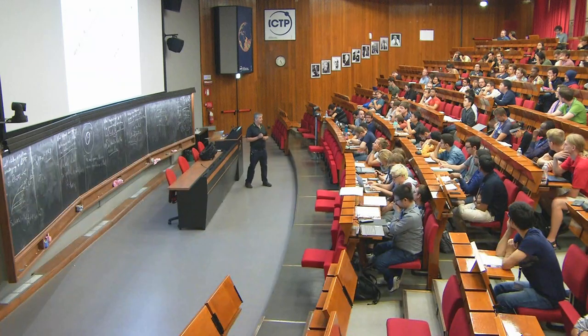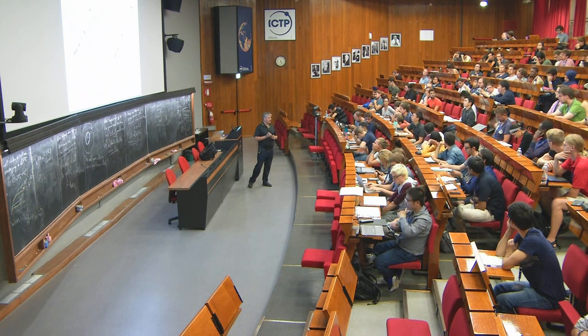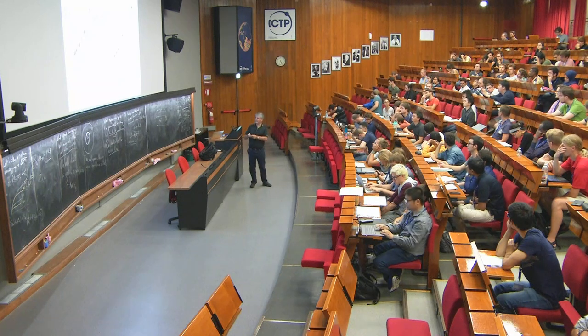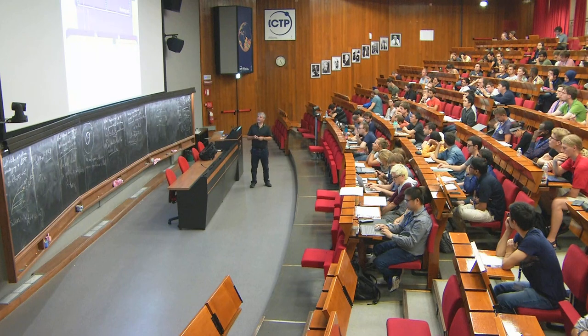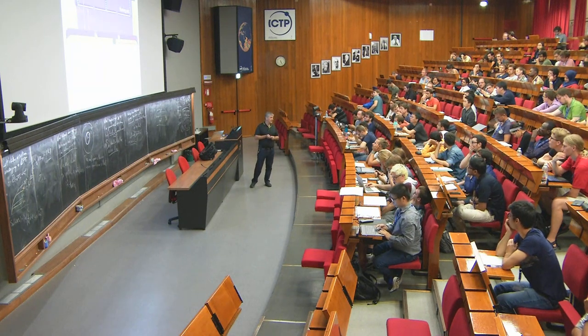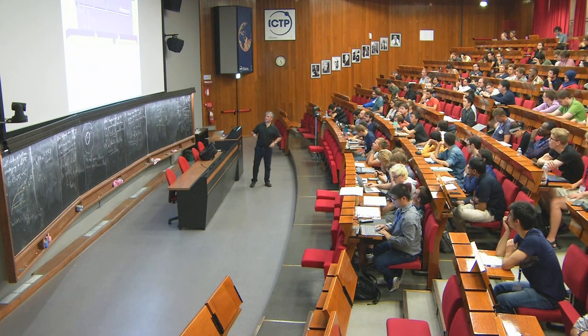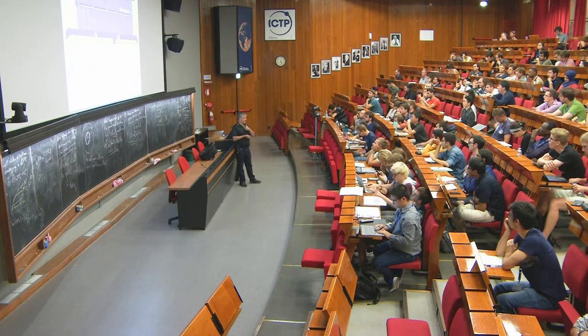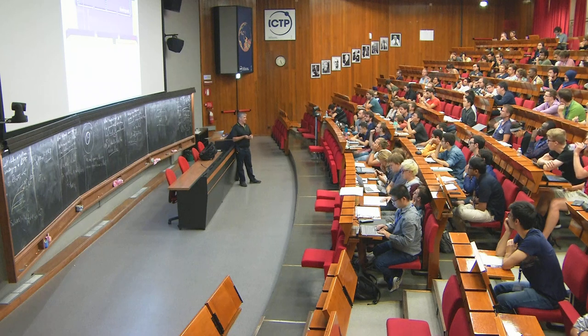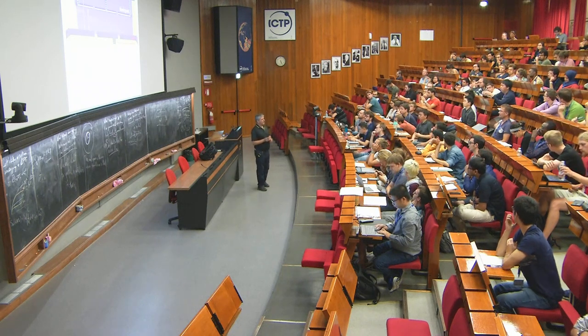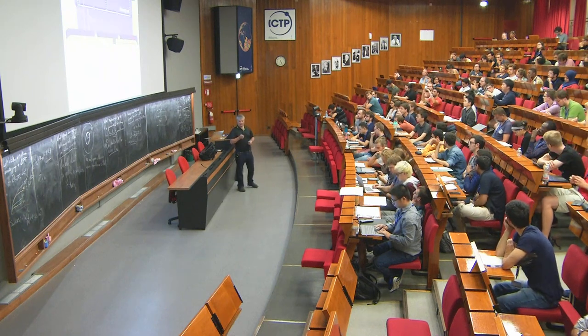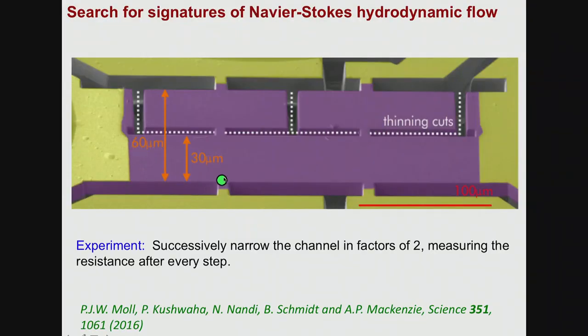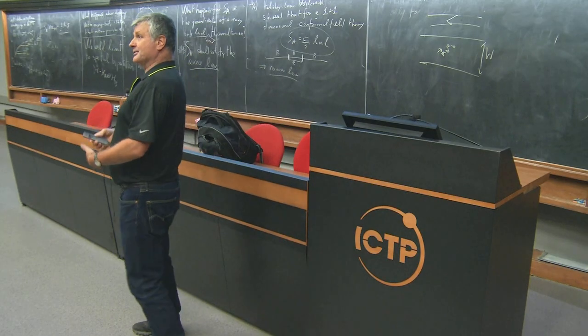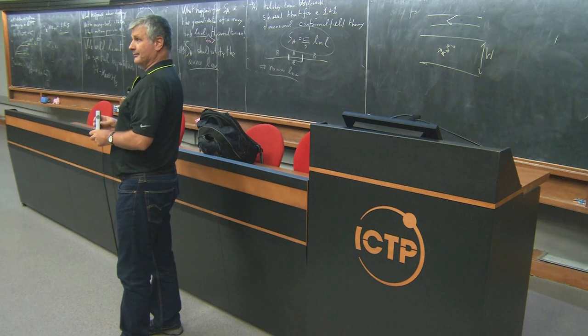Yes? Yeah, so the widths we did, we went 60, 30, 15, 8, 4, 2, 1, and then we actually had a point at 700 nanometers width as well. Yeah, this is only one of, this is the first cut. Then he kept on cutting, so by the end you had something where everything had been blasted away and you just had a very narrow wire left. For each data point, the sample came out of the cryostat, went back into the focused ion beam instrument and got cut again, yeah. Same crystal, yeah.